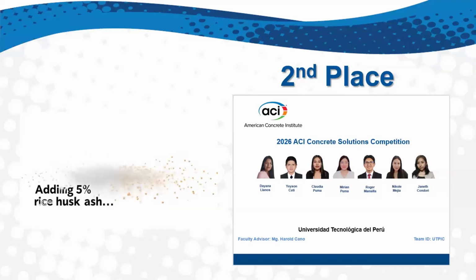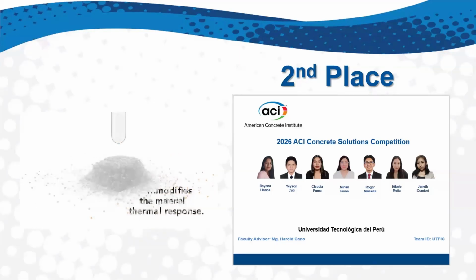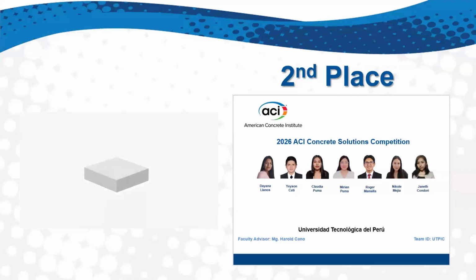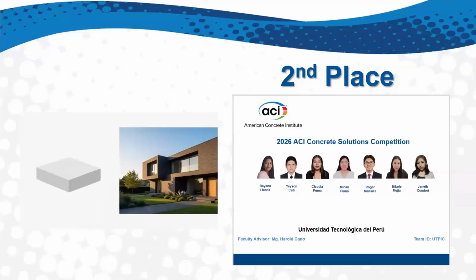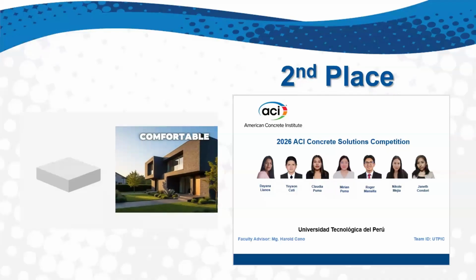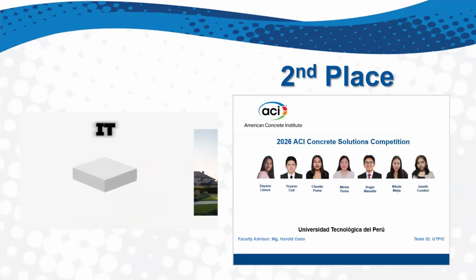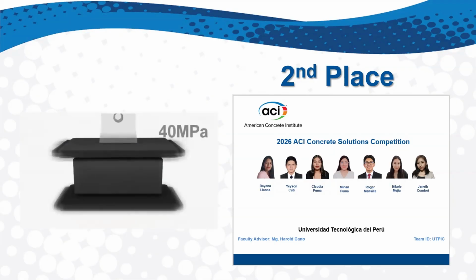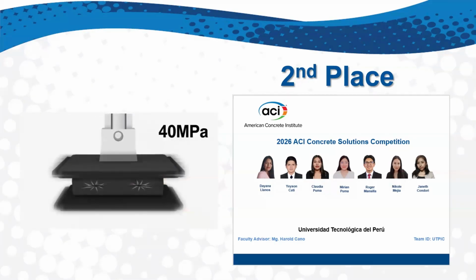By incorporating 5% of this ash into the brick powder mixture, the high content of amorphous silica manages to modify the thermal response of the material, making it comfortable and functional. At the same time, it also achieves an increase in initial strength, surpassing 40 MPa.